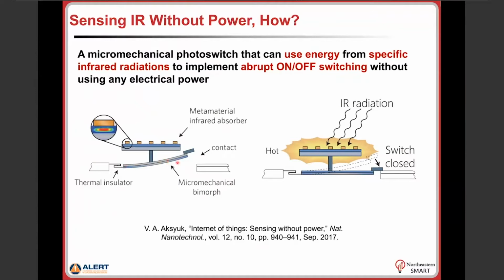So now, as you can see from this schematic representation, this bimorph cantilever at one end has a contact tip, while at the other end it is connected to the substrate through a thermal insulator, a thermally insulating region. Also, in this schematic representation, you can see that integrated on the top surface of this cantilever, there is a metamaterial infrared absorber. This is a deeply sub-wavelength structure that can very effectively absorb infrared radiation at a very specific wavelength that can be lithographically defined by the geometry of these structures that we define on the top surface of the microcantilever. So this is the basic structure, and the working principle at this point is relatively simple, right?